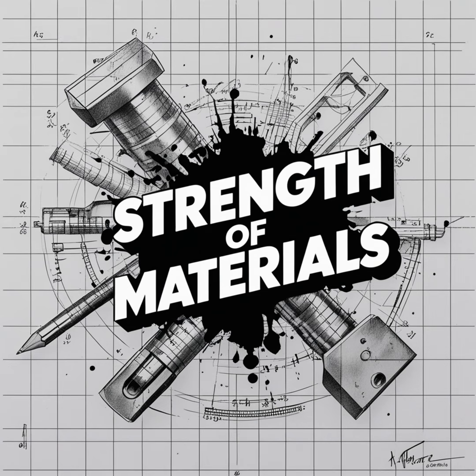To understand how we cheat, you have to understand the fundamental law of fracture mechanics. Cracks generally will not initiate, nor will they propagate, in a compressively stressed zone. Meaning what, exactly? Meaning cracks need tension to open up. Think about a crack in a piece of plastic. If you pull the plastic apart, the crack opens and tears further. But if you squeeze the plastic together, the crack is forced shut. It can't grow. Oh, obviously.